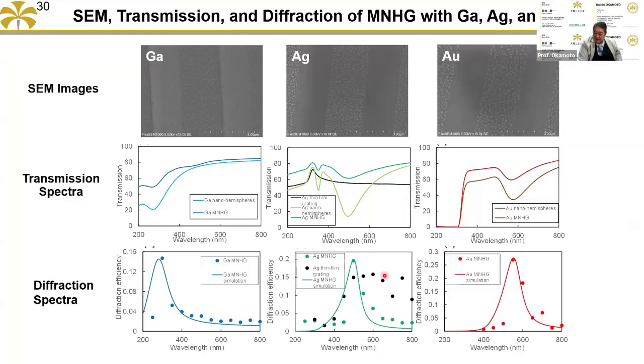And that black one is a normal silver film grating. In that case, for the UV light region, gold has no reflection, but in another visible light region, it's almost flat. But using this nanoparticle, it has some diffraction peak. That's why just this wavelength light is diffracted, and another peak is not diffracted. And we can achieve the wavelength-dependent diffraction grating.